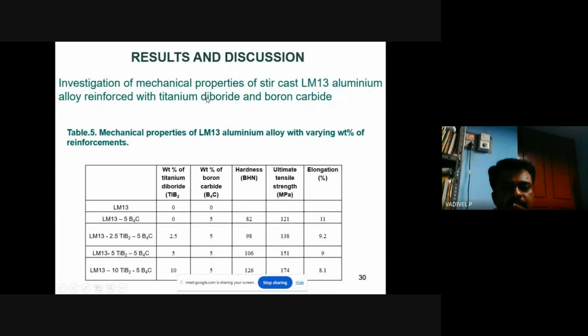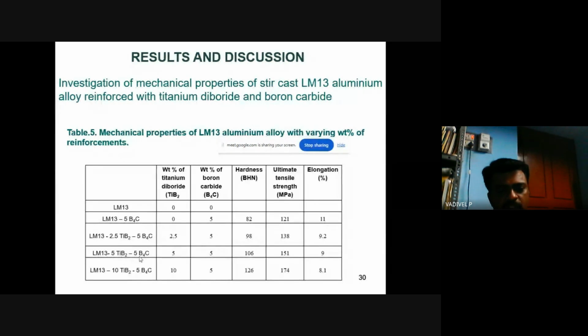So in the results discussion, we have varying percentages of reinforcement in the aluminum alloy. Okay, here on the left side you can see the LM13 aluminum, that is pure aluminum, and here LM13 with 5 weight percentage of boron carbide. Then in the third line, it is LM13 with 2.5 weight percentage of TiB2 and 5 weight percentage of boron carbide. And the fourth one is LM13 with 5 TiB2 and 5 B4C. And the last one is 10 TiB2 and 5 boron carbide. And the weight percentage of titanium diboride is 0 to 10, and the weight percentage of boron carbide is 0 to 5.